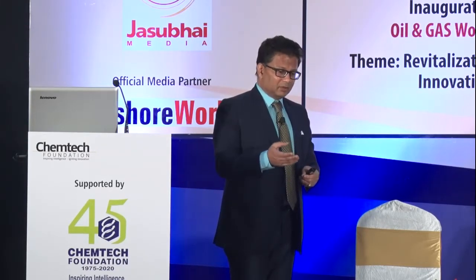This is a BP refinery in Washington State. They have a coker calciner that processes the green coke to make needle-shaped coke for other applications in the alumina industry. They have very huge corrosion, as you can see with the reheater, coming from vanadium attack at 850 degrees Celsius. They tried every metallurgy, every solution, and it didn't work because the chemical corrosion efficiency loss was so big. We happened to meet them at one conference, and they said, we tried everything, so let's give your technology a try.